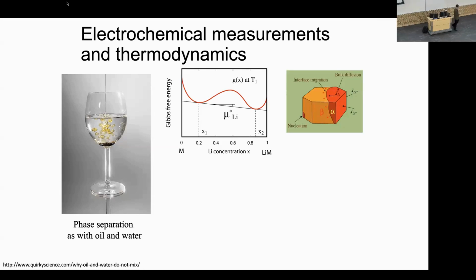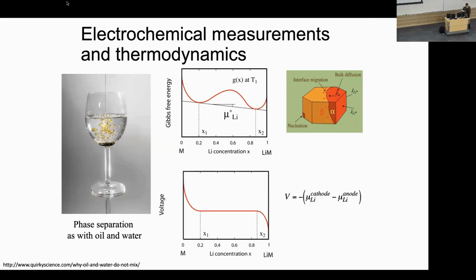And so these battery materials do the same thing when they have a free energy like this. When you're inserting lithium, you're going in from here in this direction, and you first form a solid solution, but then you have to go through this two-phase region, which means you have a two-phase reaction where you have a sharp interface separating one phase, let's say the alpha phase, from another phase, let's say the beta phase. So you get this two-phase reaction when you get a free energy that creates a miscibility gap like that.